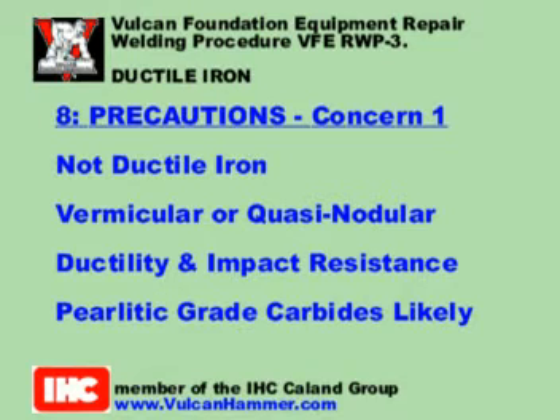The welding of ductile iron presents two problems. Concern 1. The base metal when melted at the fusion zone will not re-solidify as ductile iron, the graphite will precipitate as vermicular or quasi-nodular. The ductility and impact resistance will be reduced about 50%, and some carbides are likely to form, particularly in the pearlite grade.